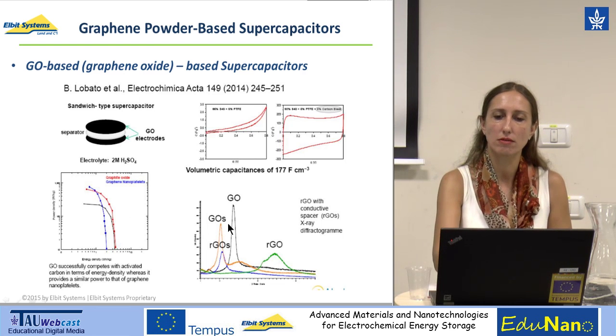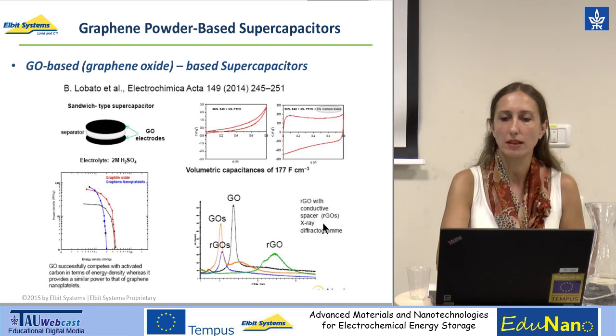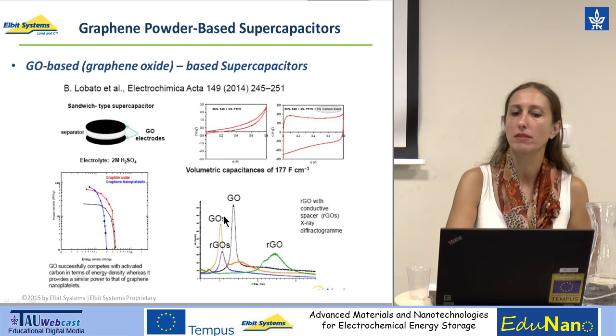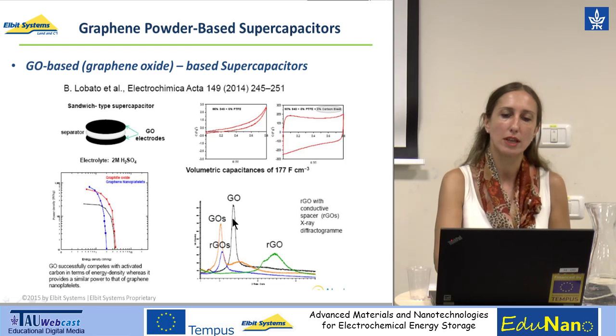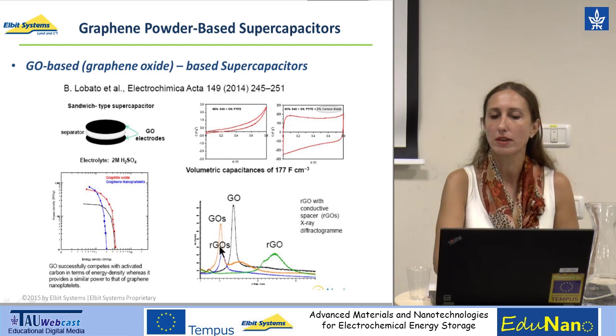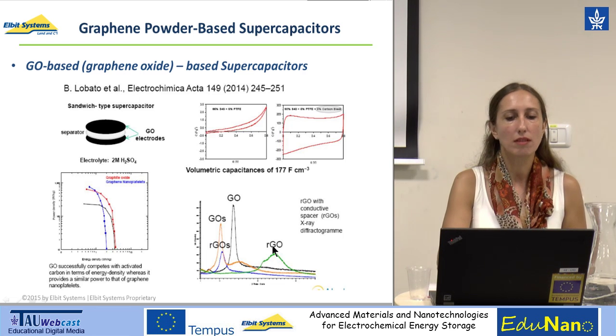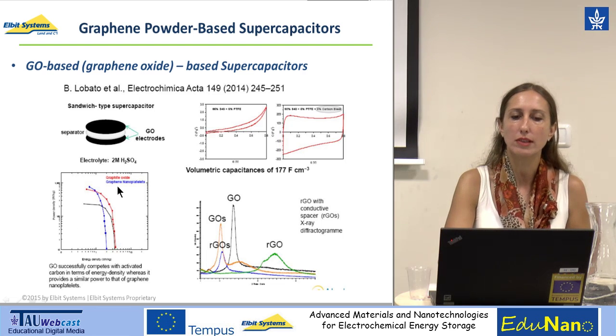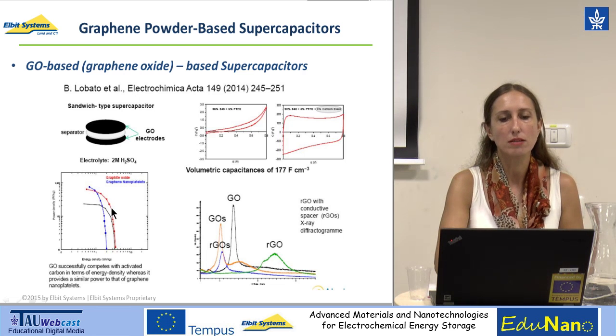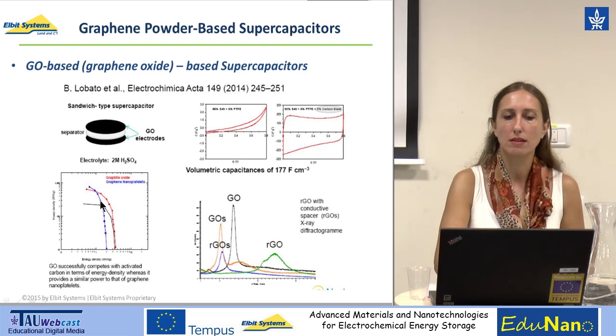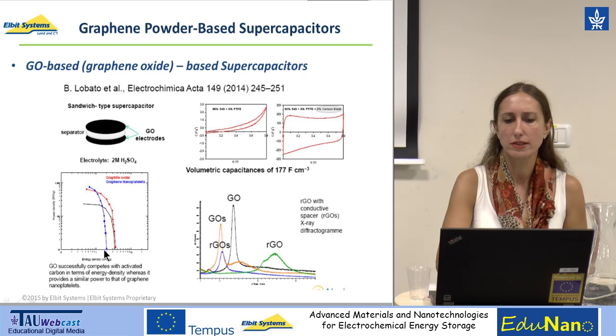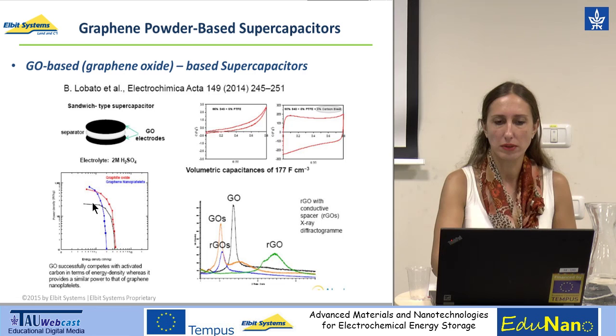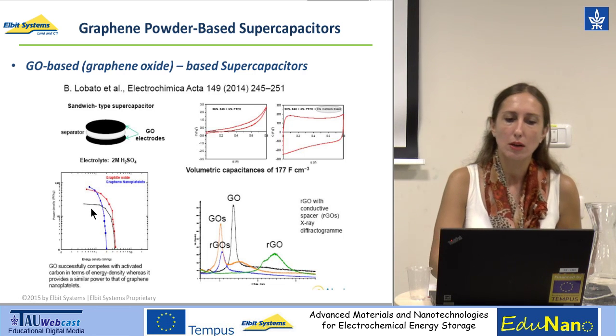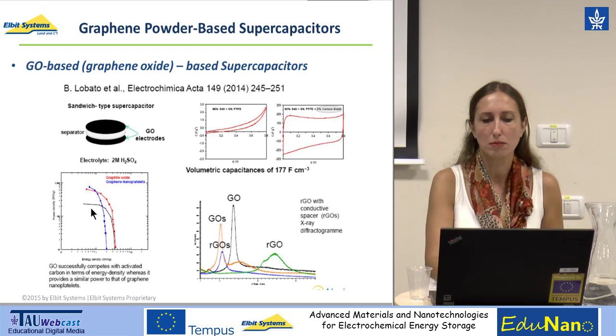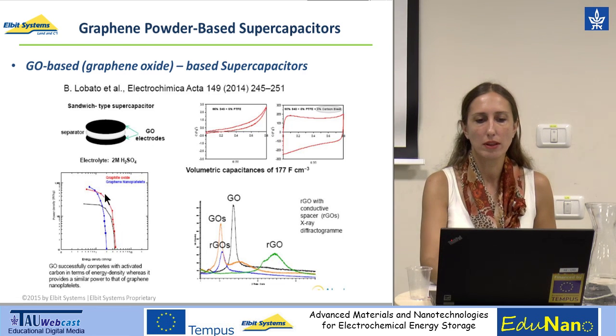What is also shown in this graph is the reduced graphene oxide conductive spacer, or RGO. It is an X-ray diffractogram of the reduced graphene oxide in comparison to the graphene oxide. So we have the initial peaks of graphene oxide nanoparticles and the reduced graphene oxide conductive spacers. When we look at the Ragone plot of the graphene oxide versus the graphene nanoparticles, the graphene oxide is the red curve over here, and the graphene nanoplatelets are the blue curve over here. We have the power versus the energy density, the Ragone plot. In black is the activated carbon. We can see that the graphene oxide successfully competes with the activated carbon in terms of the energy density, and on the other hand, it provides a similar power to that of graphene nanoplatelets.